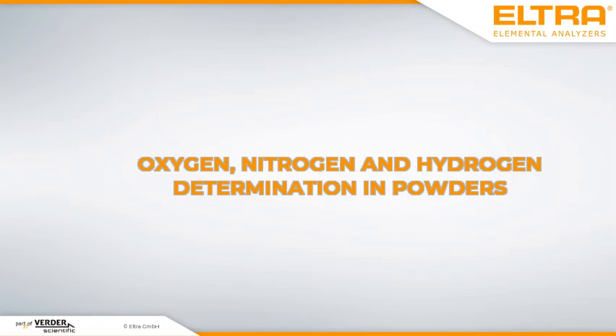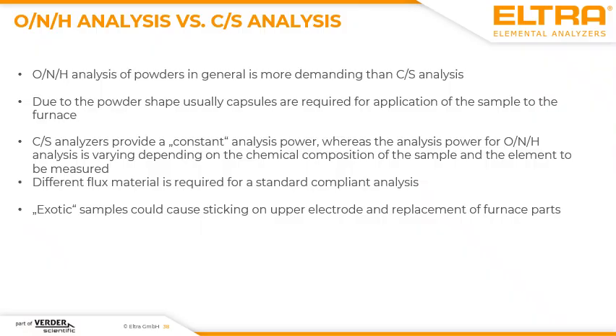When we are now talking about correct oxygen, nitrogen, and hydrogen analysis, on the one hand, the problems are the same, but on the other, we have other difficulties because the chemical composition and applied sample weight is something different for an ONH analyzer in comparison to a CS analyzer. Please consider that when you are using a carbon sulfur analyzer and an ONH analyzer, the problems for unknown powder analysis could be a little bit different. For ONH analyzers, powdered samples usually have to be applied in a capsule, which means a reduced sample weight but also could mean an additional risk for blank values.